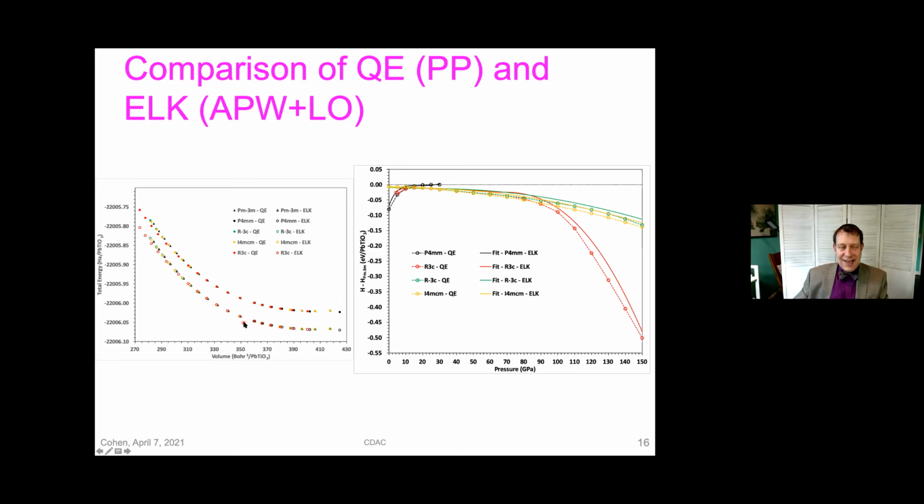The other thing you can see here, because the pseudopotential results are all on this curve, is that if you only look at the total scale of the energy, you see all these ferroelectric phases, and you wouldn't be able to see any difference in them whatsoever. They fall just along what looks like a smooth equation of state. So the ferroelectric energy scale is an order of magnitude smaller than the normal compression energy scale that one's thinking of in normal kinds of phase transitions.